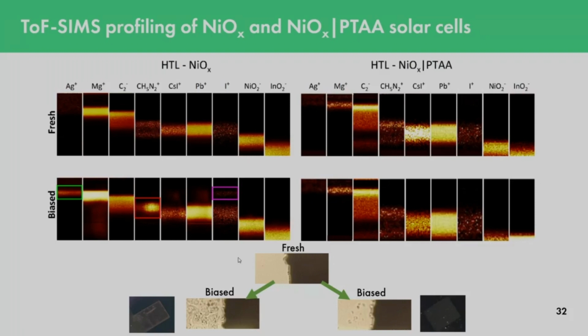And you can also observe on these microscopic photos at the bottom that a fresh device, which was really beautiful and smooth, after the biasing for nickel oxide material became rather rough and of bad quality, with a lot of pinholes actually.